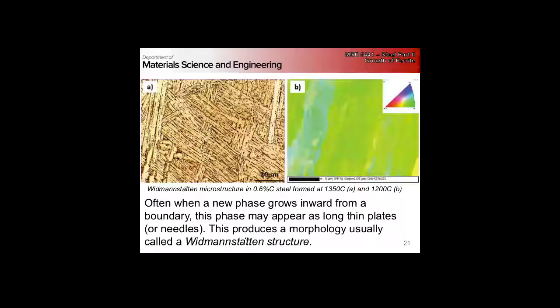So here we see two different Widmanstatten structures characterized by two different techniques. What you notice about these are sort of long, needle-like structures. This looks an awful lot like structures we'll see again in titanium, the alpha beta. But basically what's happening here is we've got this ferrite that is growing inward from the boundary. It's going to appear as long, thin plates or needles.